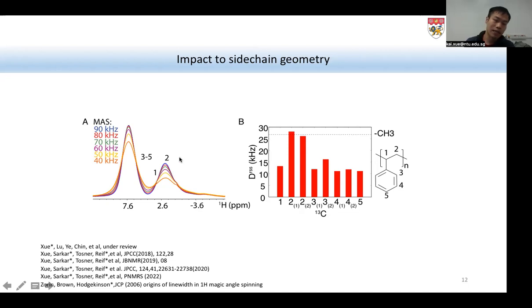This is definitely related to the proton-proton dipolar couplings, the local dipolar coupling environment, and we resort to a concept proposed by Brown and Hodgkinson in 2006. They call it DRSS. Let's say we have a proton spin here. The dipolar couplings between this proton and its neighbors on one side, we take the square of them, sum them up for all the protons nearby, and then take the square root of the sum and calculate the value. We found that aromatic protons, and also the CH group, have much smaller DRSS values than the methylene groups.